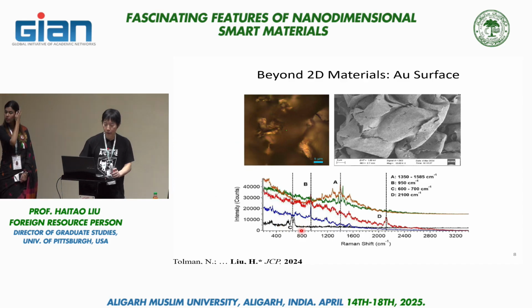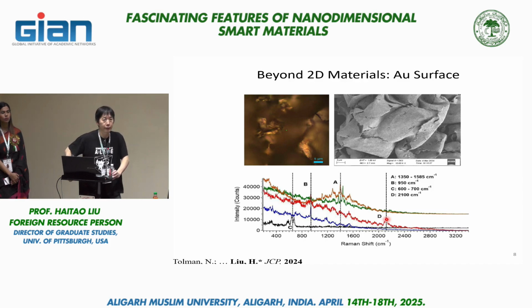Okay, so for example, this is some kind of branched carbon chain structure. This one is related to some kind of carbonyl structure, and this one, as I said, is carbon monoxide. This seems to be some kind of thermal decomposition product coming from the contaminant. Now, in the ellipsometry measurement where we showed the buildup of the contamination layer, ellipsometry unfortunately doesn't provide any chemical information. All the modeling is made with the assumption of a certain refractive index, so we cannot know for sure exactly what kind of contaminant is there.